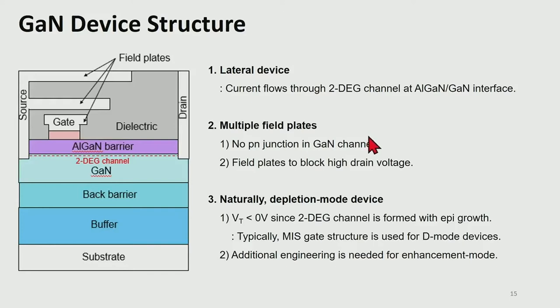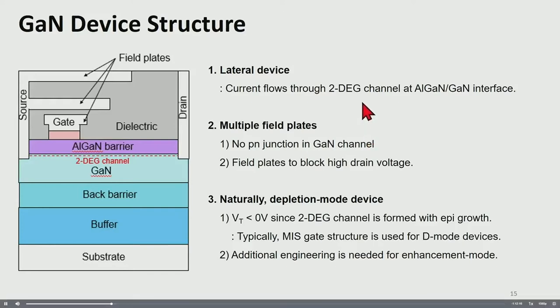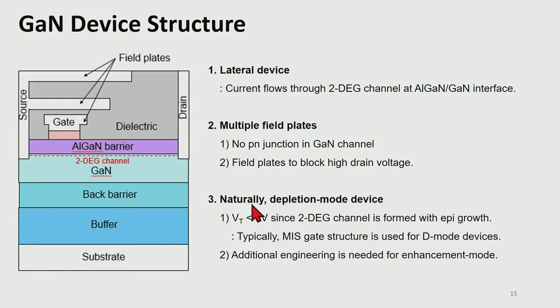So once the epi growth is done, now we can fabricate the device on it. And this left figure shows a typical GaN device structure. So first thing you can notice is that it's a lateral device. So current flows laterally through this 2DEG channel. In the GaN channel, there is no PN junction. So typically for GaN device fabrication, people do not use implantation for additional doping.